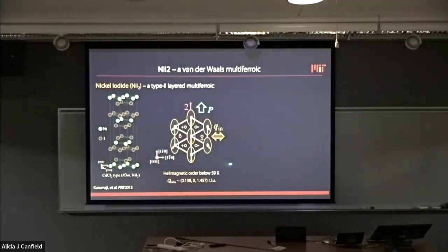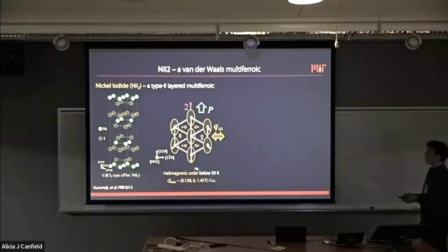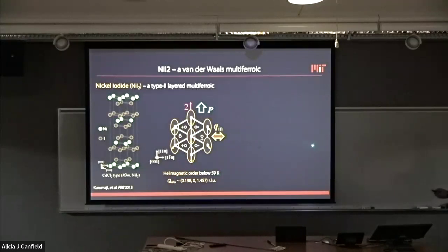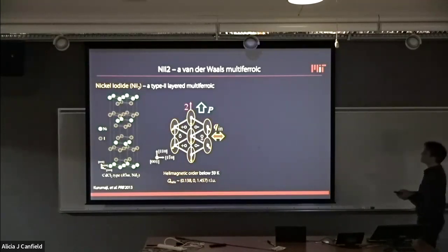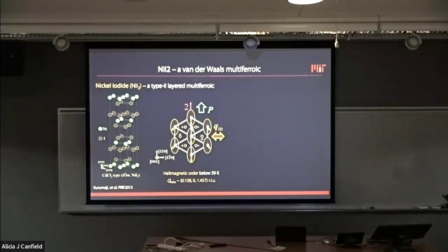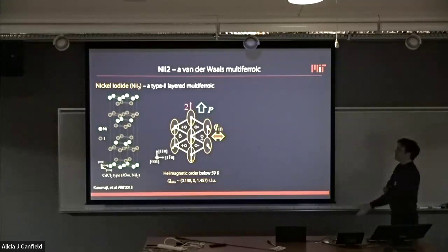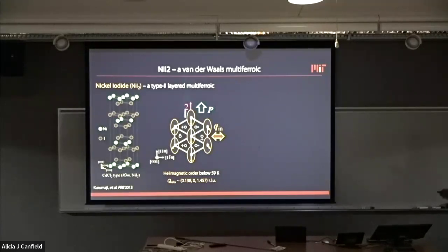At low temperature, the material develops helimagnetic order below 59 Kelvin in the bulk. The pitch of the helix is about 7 unit cells in the plane and about 3 unit cells out of the plane. This is just shown in the plane, but the helix is actually propagating out of the plane as well. And remarkably, what happens when the system goes into the spin helical state is it loses all of its symmetry operations except for one two-fold axis. So it becomes very low symmetry, which is what enables it to be both polar and chiral. It retains one fundamental symmetry, the two-fold rotation, because that is what allows the electrical polarization, which has to be along that axis.